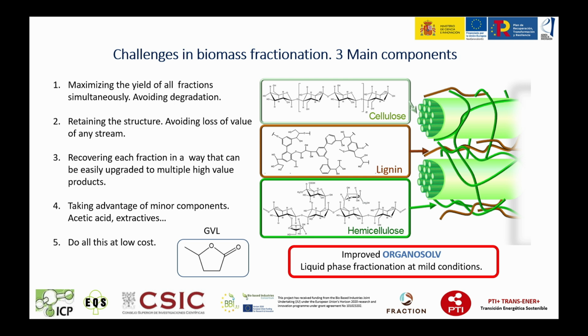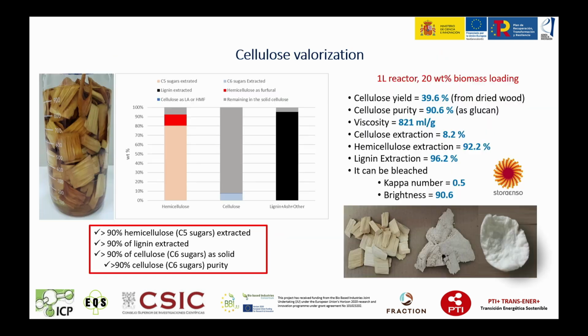avoid loss of value, and recovering each fraction in an easy way to apply it in different processes. Also taking advantage of minor components such as acetic acid, and of course do all this at low cost. In this way, we perform an organosolv process, which is a biomass fractionation process where we use GVL, which is an organic solvent in liquid phase and mild conditions.